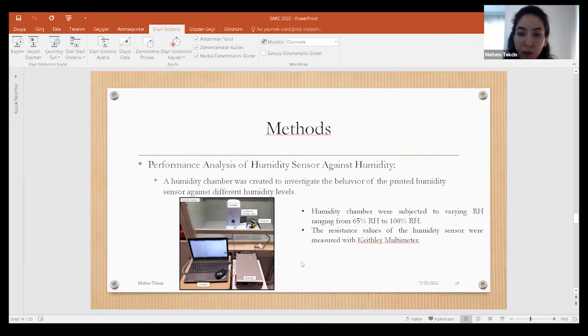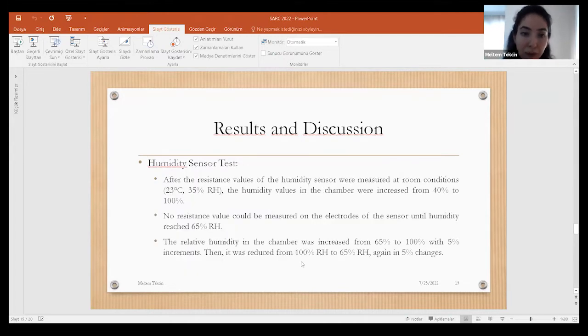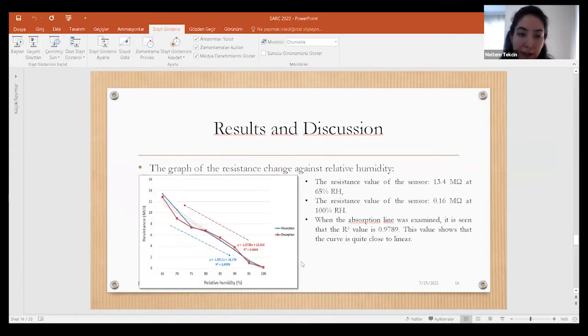The humidity chamber was subjected to varying relative humidity ranging from 65% to 100%. The resistance values of the humidity sensor were measured with a Keithley multimeter. After the resistance values of the humidity sensor were measured at room conditions, the humidity values in the chamber were increased from 40% to 100%, but no resistance value could be measured on the electrode of the sensor until humidity reached 65%. The relative humidity in the chamber was increased from 65% to 100%, then reduced from 100% back to 65% relative humidity. Here we can see the resistance versus relative humidity graph of the humidity sensor.